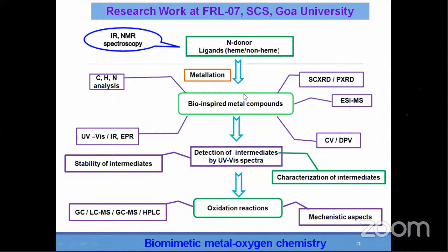Once we know the compounds are very pure and the composition is known, the next step is to see whether some intermediates are forming. As I mentioned earlier, we trace these intermediates by simple UV-visible spectroscopy. We have this Agilent 8453 spectrophotometer, which I used earlier in my postdoc, along with cyclic voltammetry and other things. So we do initial characterization and then try to stabilize the intermediate. Of course, because of limitations in infrastructure like a cryostat, low temperature studies are not possible at the moment. Wherever possible, we send samples outside, but we do some characterization studies. In my laboratory we have characterized some compounds formed at room temperature, and that is what I am going to show you.